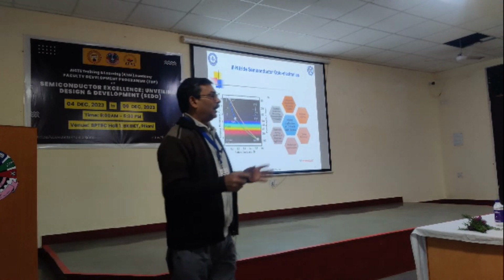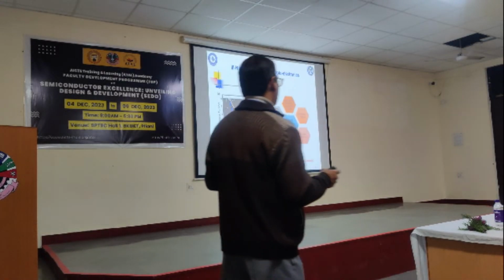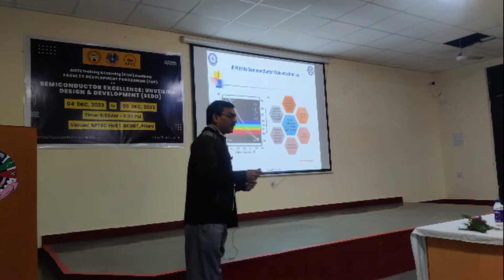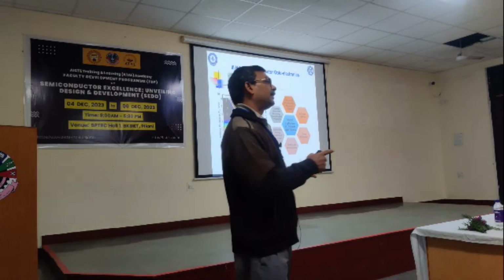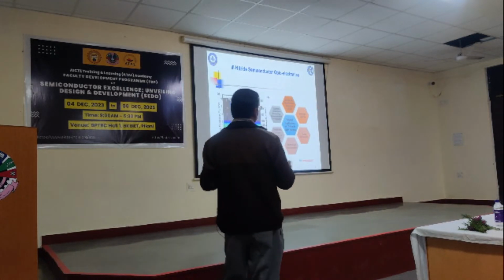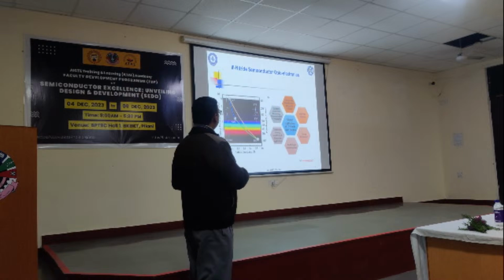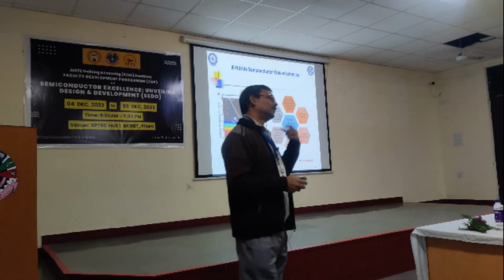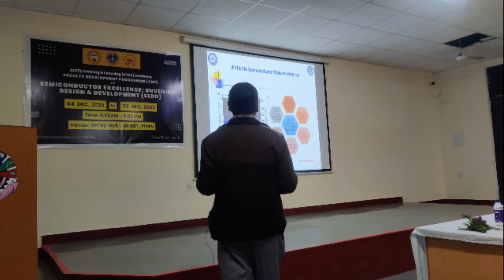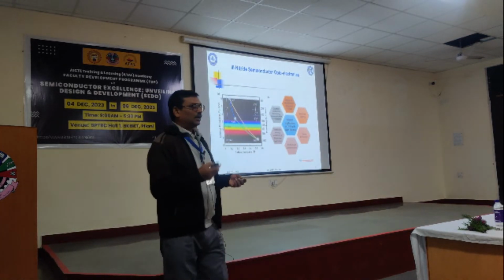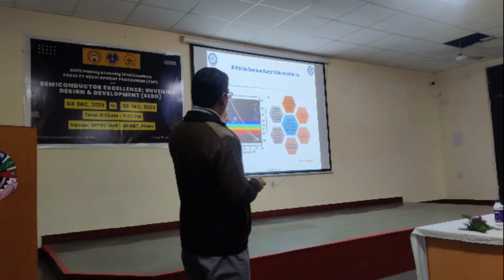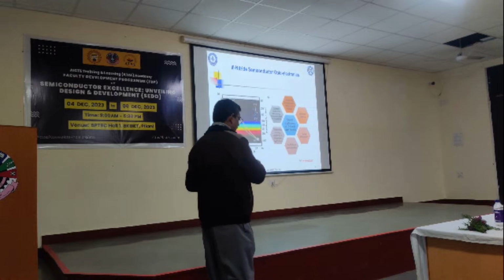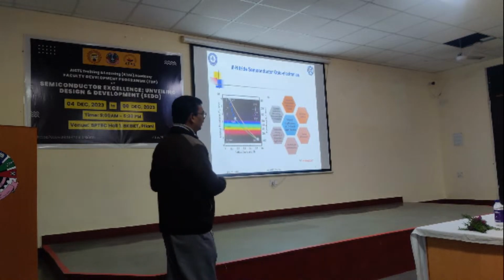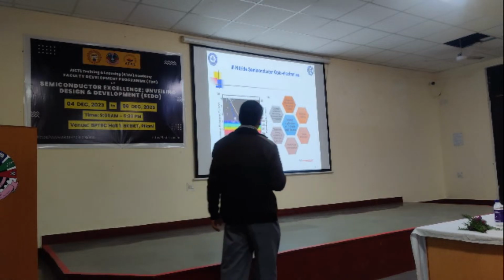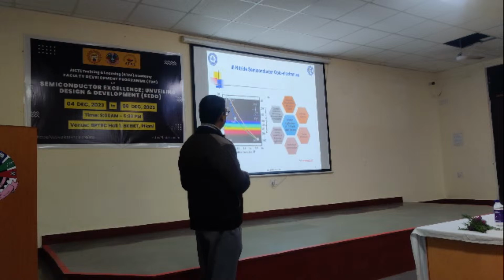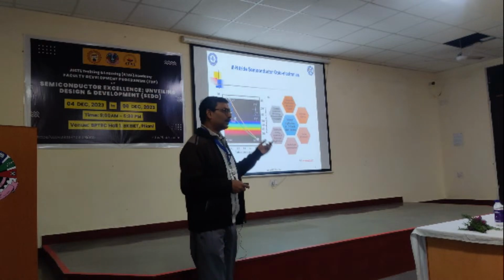But at present this is also an area of contemporary research, because it is theoretically possible, but the efficiency nowadays is again below 5%. And if we go higher and higher towards the UV range, the efficiency goes lower and lower. So there are much more difficulties there. Unless we have some breakthrough, it is very difficult to get that high efficiency UV light. But in the visible range or near UV range, obviously it is very much useful. In the high UV range also it is very much useful, but in terms of efficiency, it is difficult.